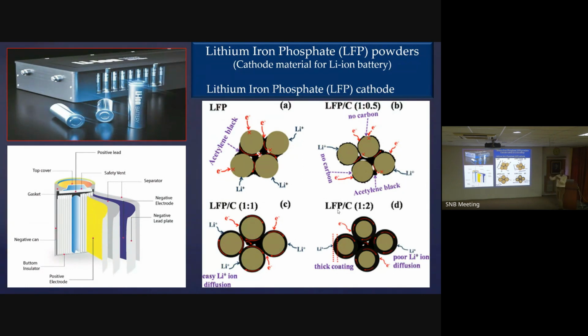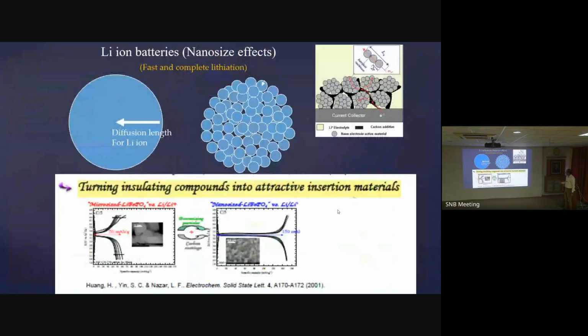Initially we had a two-step process. We made lithium iron phosphate by flame spray pyrolysis at the kilogram level, and we coated carbon in the second step, and it was quite successful. It's on par with global benchmark products. But the unfortunate thing is, it's too expensive and no one was ready to come. We spent almost 5 years, but no one was ready to take the technology. Then we started a solid state process where in one step we have carbon coated material, and it took another 2-3 years to make that, and now we are ready.